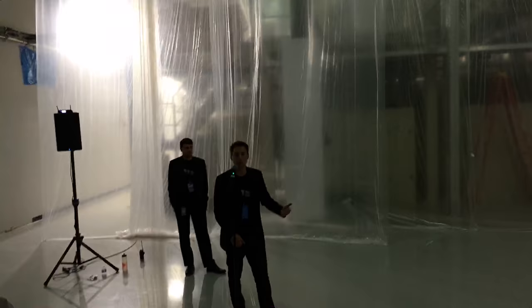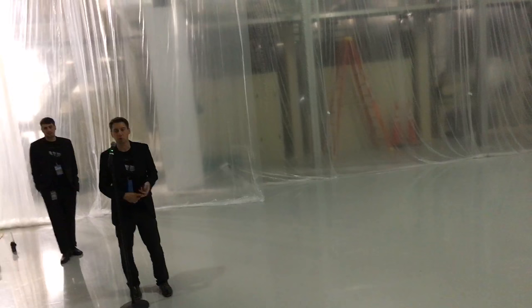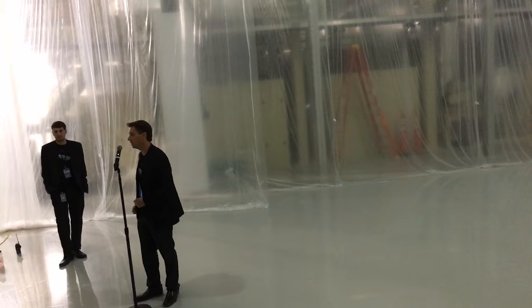this oven. Every one of these booths has an airflow inlet and airflow outlet at a very prescribed temperature and flow rate in order to control the evaporation rate as that foil comes down the oven. By the time it gets here, we again have dry active material on the top of the substrate.